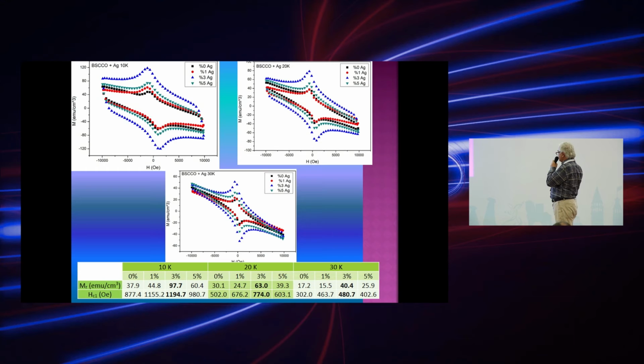And from these figures, we have analyzed remnant magnetization and the critical field, and we have tabulated them here. You can see that 3% of the silver has a big remnant magnetization and also critical field in comparison to the others.